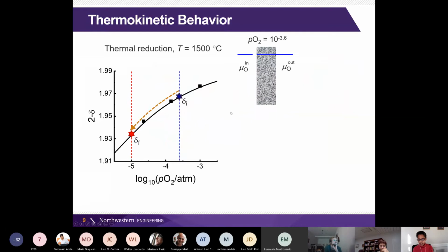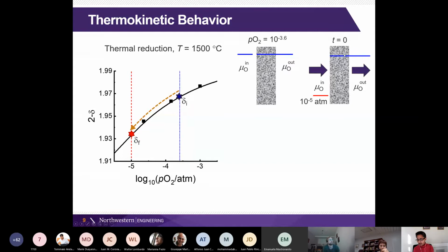Let's look at our material, and before we go into the mathematical model, just look at what it means in a physical sense. That means that we did the oxidation here with this steam, so the chemical potential in and out are the same once we are completed with the oxidation step. So now as we initiate the reduction step, we have this low oxygen chemical potential gas coming in, and before any gas goes through, we're still at this state for the exhaust and for the material.